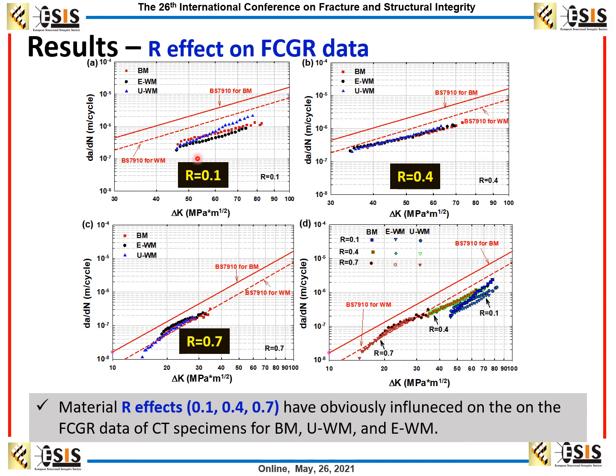It also can be observed that the FCGR in the BM and the WM becomes faster as the R ratio increases, which is consistent with the consensus on the R ratio effect for most metallic material. So the material and R ratio have obvious influence on the FCGR data of CT specimen for base metal, undermatched weldment and even matched weldment.